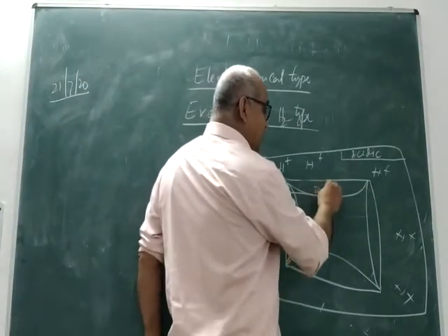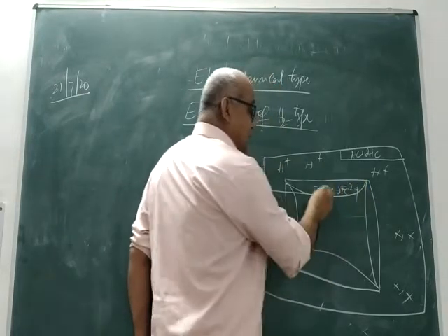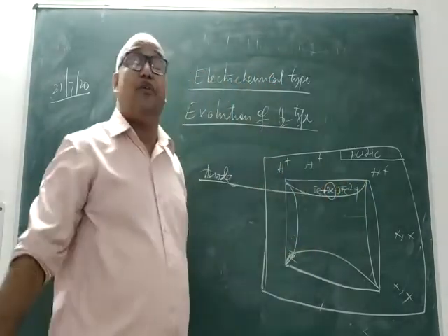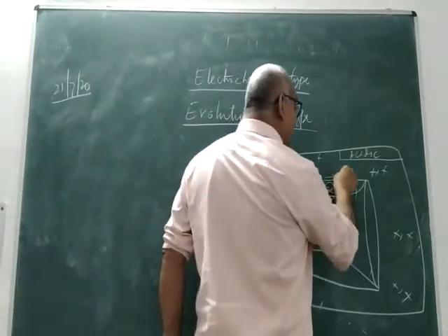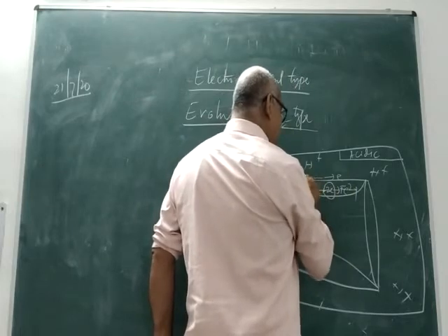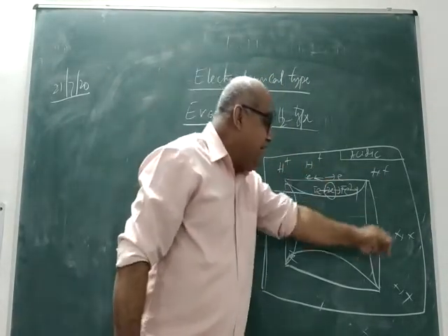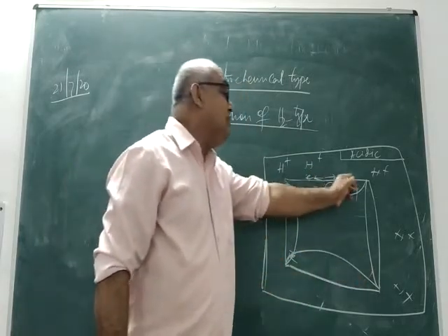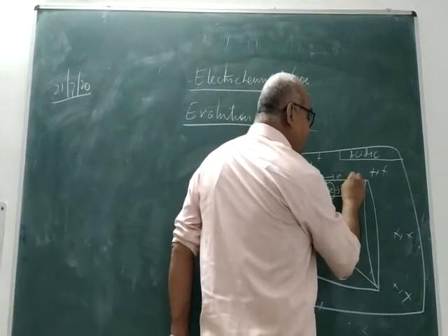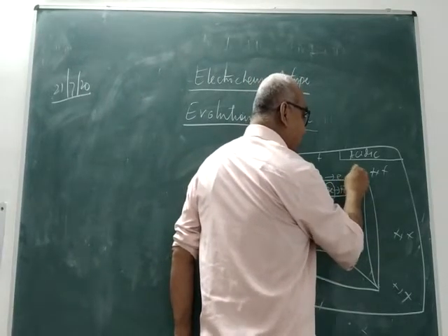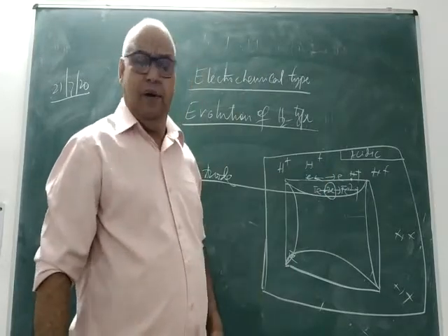Iron will give up 2 electrons to produce Fe2+, oxidation. Now the electrons being released here due to oxidation, due to the anodic reaction in fact, will move there on the surface. Being acidic in nature, H+ ions will be there all along. Suppose this is the point where this electron meets a proton, that is a hydrogen ion.